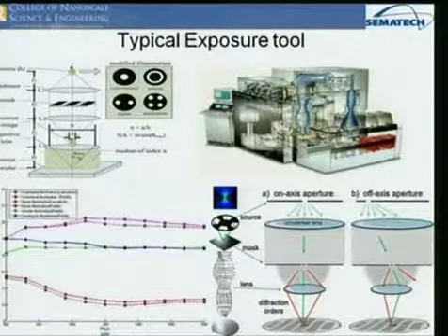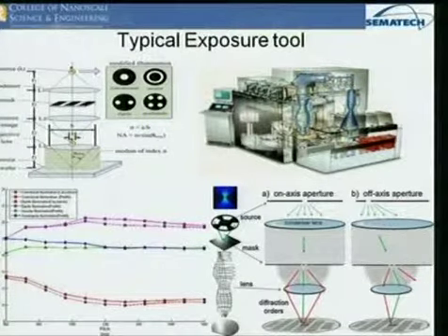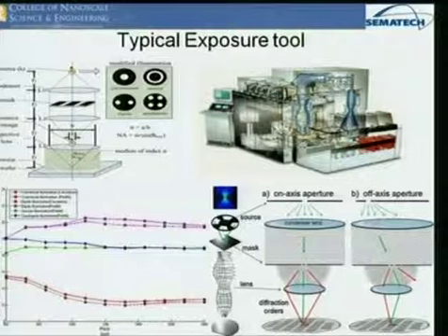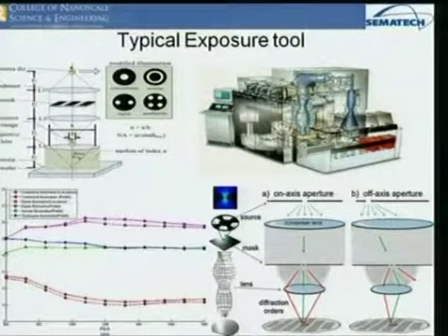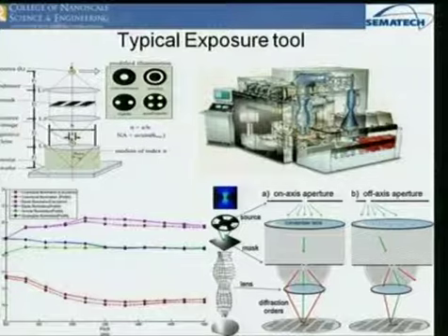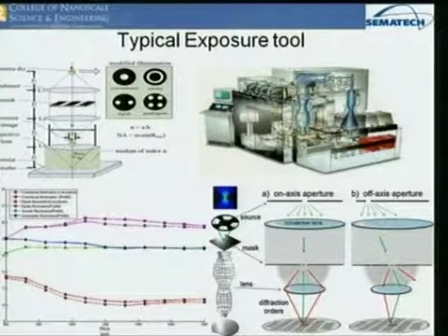So as I mentioned, we use different light to get different features to print. This is an example of what happens when you use these different illumination systems. So for example, the conventional illumination here is shown in red. It's the worst, right? It prints this small features, this small range. What we want is higher and longer. And you see the best one we get here is dipole, and I mentioned that. Catching those two orders gives us really the best.